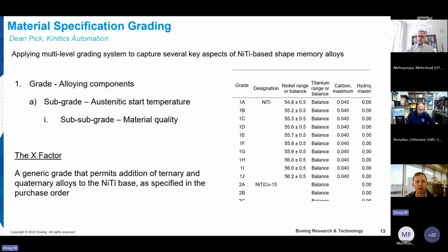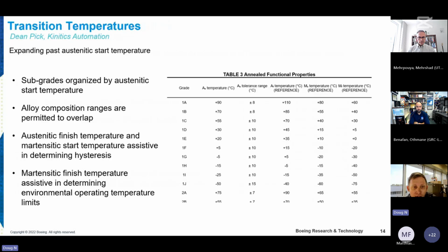And we kind of are leveraging the way that titanium alloys, conventional titanium alloys are graded within ASTM standard specifications. All right. So grades are organized by austenitic temperature, austenitic start temperature. F2063 specifies As as a requirement. However, we also want to expand to the other transformation temperatures because we care about hysteresis through the thermal cycle. And note that they're just references here.